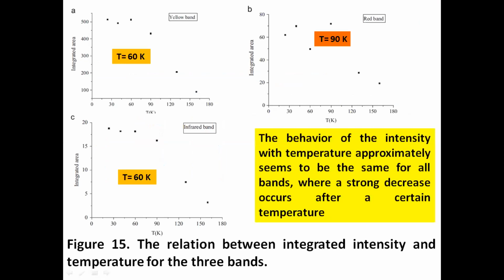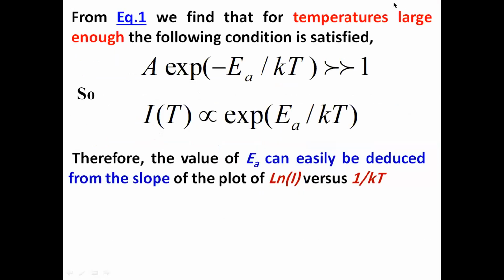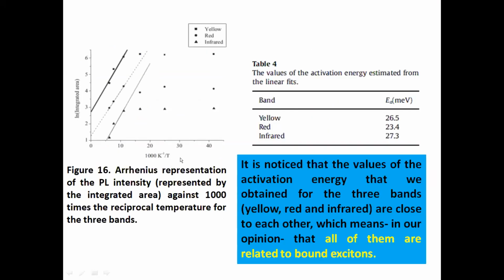Okay, now integrated area is plotted against temperature, and you see the decrease in integrated area with temperature for the 3 bands. Now, as I said, the exponential factor becomes larger than 1, and here we got this relation. Then a plot of the natural logarithm of the intensity against reciprocal temperature is performed. This is known as an Arrhenius plot, from which the activation energy was evaluated. It is found in the 20s, and this means these bands are related to bound excitons.